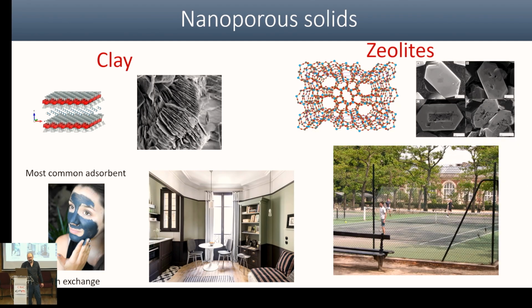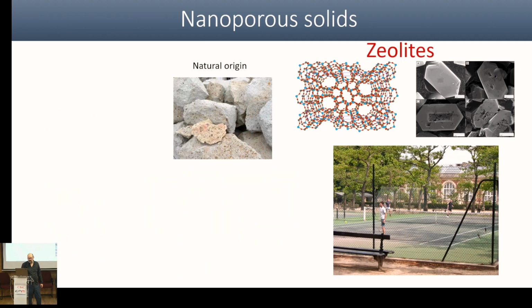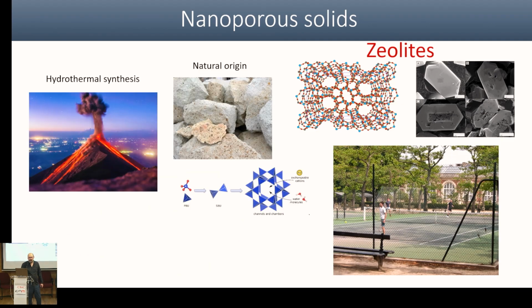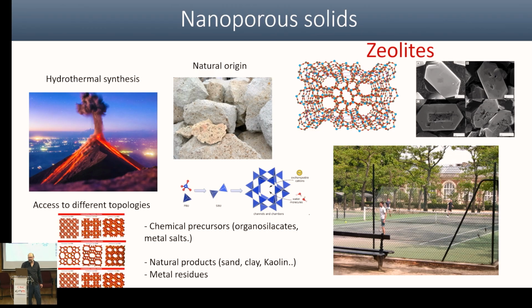Then we move to zeolites, where we can play tennis inside 1 gram, okay? They are around 300 square meters per gram typically. We have some highlighting developments inside ICMM, so they break all the records. But typically we move in that range. They are of natural origin, but we can also prepare them synthetically. They are prepared by hydrothermal synthesis, okay?